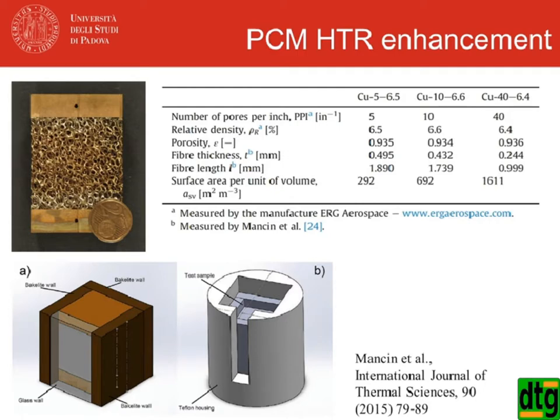PCM. This is an extremely important characteristic because, as you know, by inserting enhanced surfaces inside our storage, we limit the volume which can be filled by the PCM. So we reduce the capacity of our storage. But when we use a metal foam or a different cellular structure material, as you will see in the next slide, you just remove 5 or 7% of the entire volume, and the entire space can be dedicated or filled with the PCM. But you can enhance the heat transfer by 20 or 30 times.